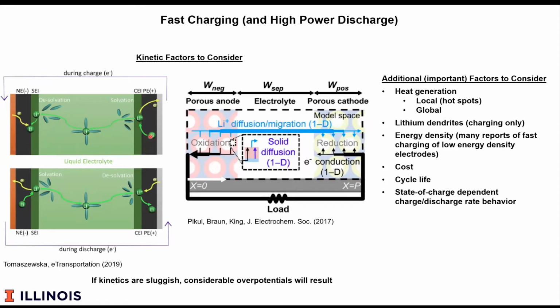Now at the cathode, what's occurring is that the lithium is now leaving the cathode. The cathode gives up an electron in this process, and the lithium is solvated. The kinetics of the solvation are quite rapid. They tend not to be rate limiting. But the diffusion of the ions in the electrode certainly can be. During discharge, of course, the reverse is occurring.